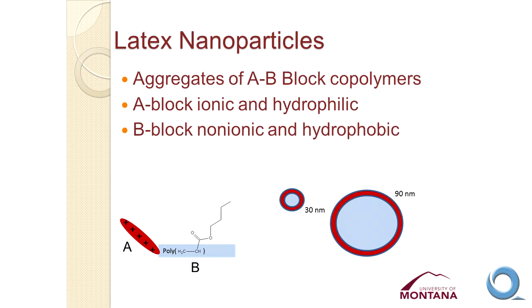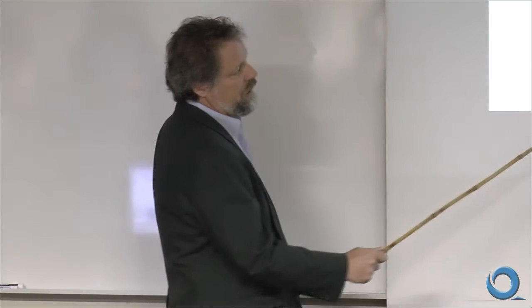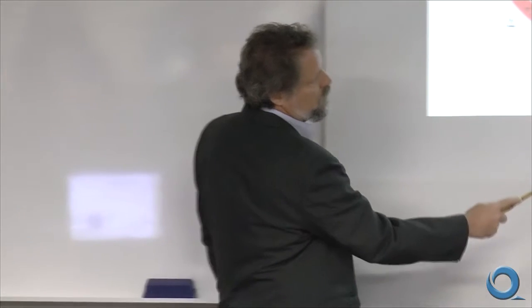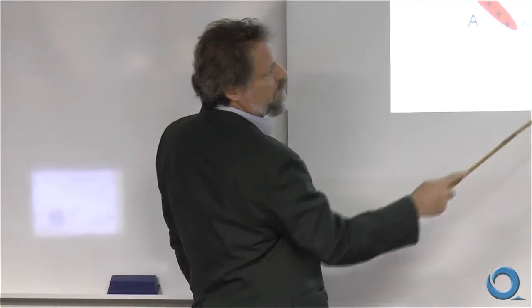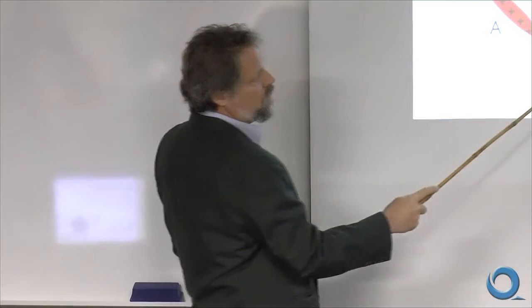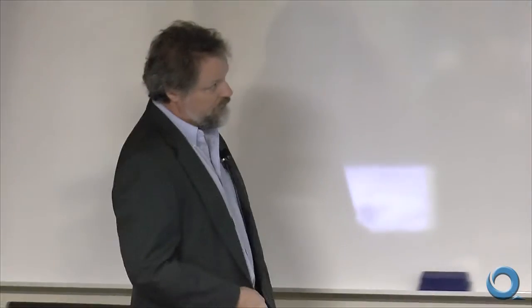And so we have an amphiphilic polymer, and these amphiphilic polymers will aggregate into nanoparticles. And we can synthesize and control the size of the nanoparticles. We do that primarily by changing the length of the hydrophobic polymer. So we can have a large hydrophobic region in the core of a large nanoparticle, or a much smaller hydrophobic region in the core of a smaller nanoparticle.